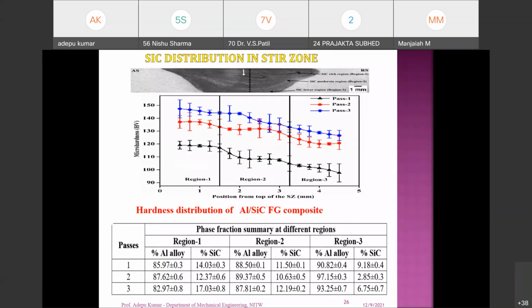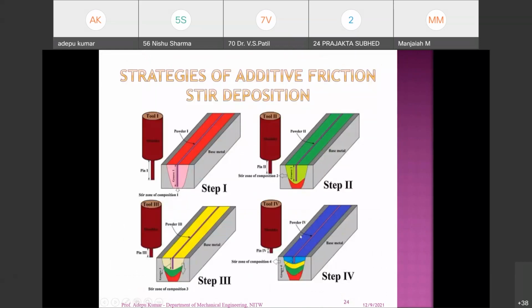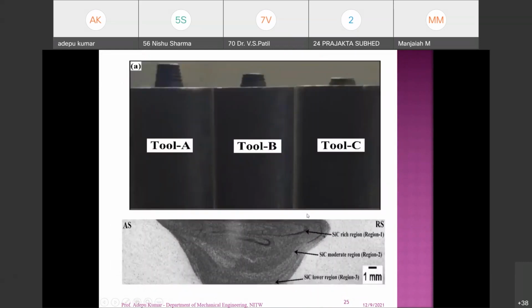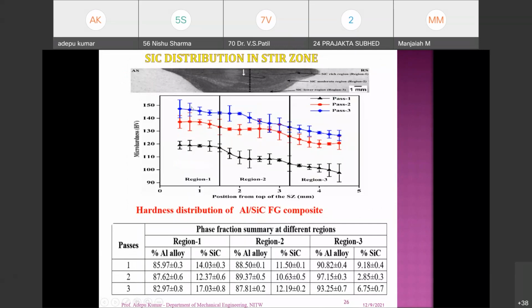So the more quantity of SiC, the more hardness. Indirectly, your hardness is higher here than this one. You can also see the hardness distribution from region 1 to region 3; this is slightly harder than this one. Further improvement was also done. He has completed not only one pass, but two repeated passes, second and third. After preparing this, he did it again without any additional reinforcement. You can apply the technique in the second and third pass so that further refinement takes place, which improves the mechanical properties.